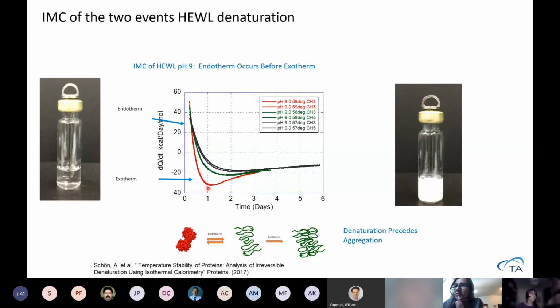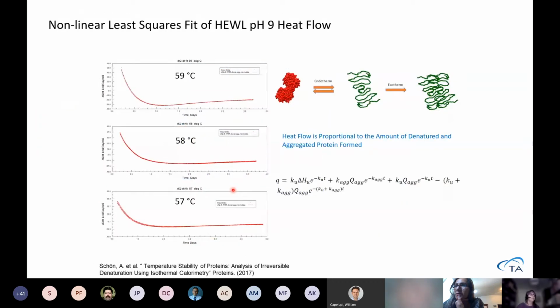This exotherm will be bigger at higher temperatures. So the process is faster. And then we can fit those, we can make models, because the heat flow, as I said, is proportional to the reaction rate. So we can have the reaction rate, or we can make a fit where we evaluate the reaction rate first for the aggregation and then for the unfolding. So that could be fitted.